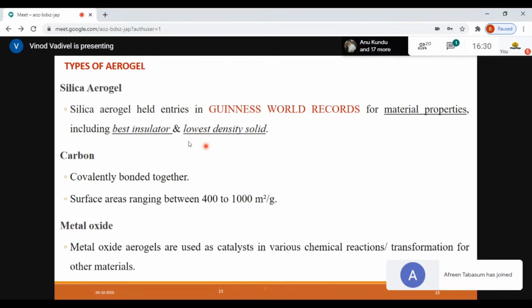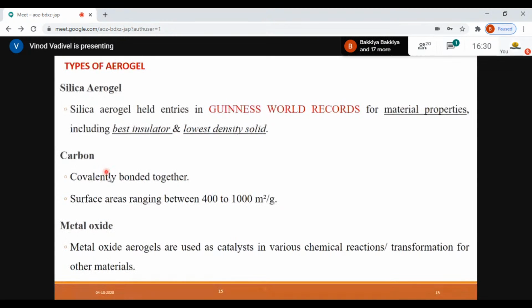And now the research is moving towards developing carbon-based aerogels, which are more covalently bound together, with surface areas ranging between 400 to 1000 square meters per gram. This carbon-based material is really interesting because you have carbon, you have porosity, you have insulation, and you can make it into any system which needs to be doped. And again, metal oxide aerogels are used as catalysts in various chemical reactions and transformations of other materials, and they generally work as dual functional materials for photocatalysis as well as adsorbent. So the intention is to adsorb the material and then act as a photocatalyst.